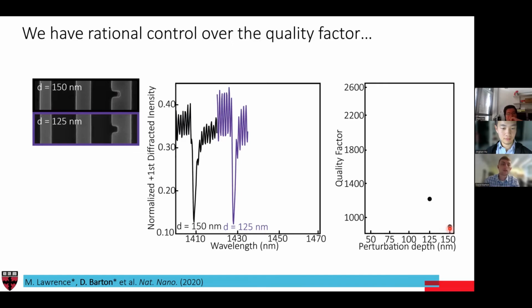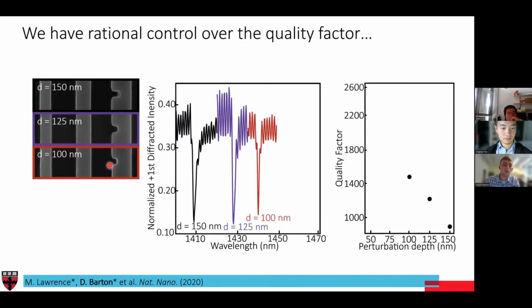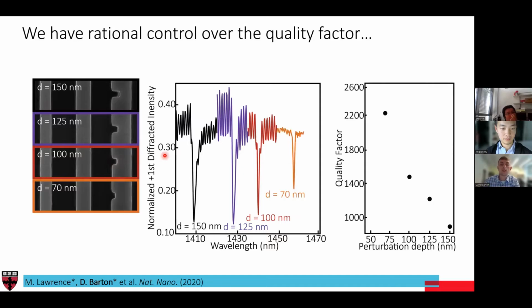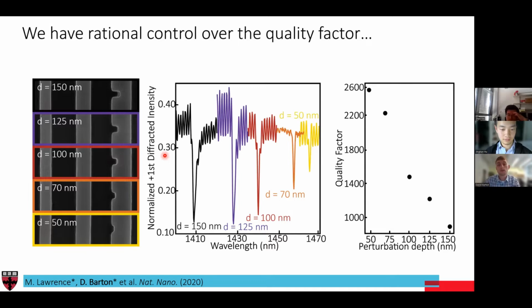If we change, for example, how strong this perturbation is, we can actually change, roughly speaking, what the quality factor is. And so as we make them smaller and smaller, the Q factor actually gets quite high, in this case about 2500, which is just dramatically higher than what you would typically have in these sorts of elements. And so this is really great. The highest Q we were able to get is about 2500.